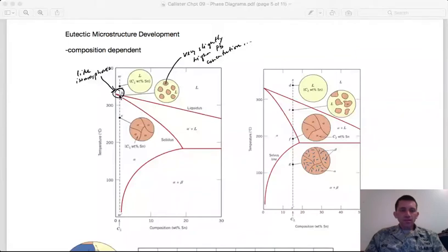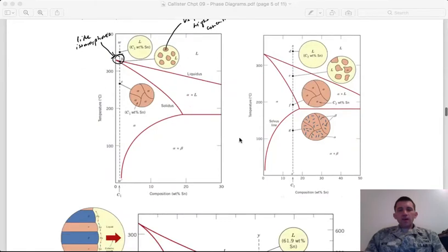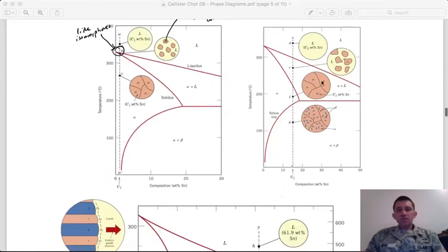And once we pass through the solidus line here, we will have it solidified completely to alpha. And since we're in this region here where we don't have any beta at all, at this low level, I can solidify all the way to room temperature, and I'll have alpha grains, and that's it. If I have a higher composition of tin, I'll start out in liquid.